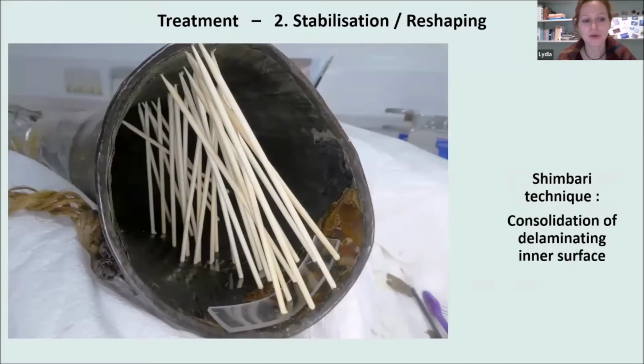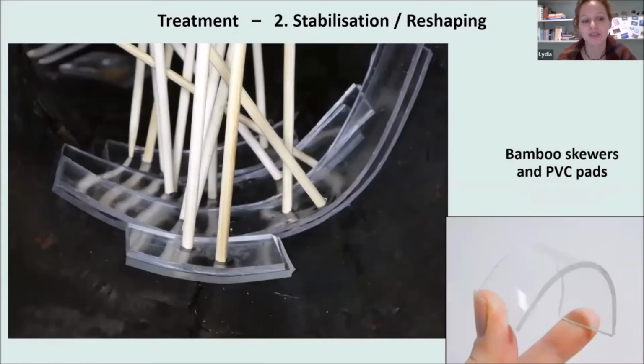On the inside of the horn, I referred to the Japanese shimbari technique. Bamboo skewers are inserted under light tension to push down the consolidated layers. A thick layer of PVC pad served as interlayer between the skewers, but also where I had to use clamps. The pad is slightly flexible and follows the shape of the horn, but is rigid enough to distribute the pressure of a skewer or clamp evenly onto the curved surface.